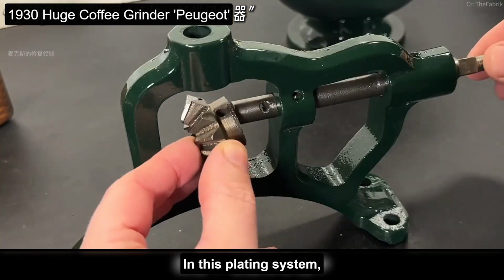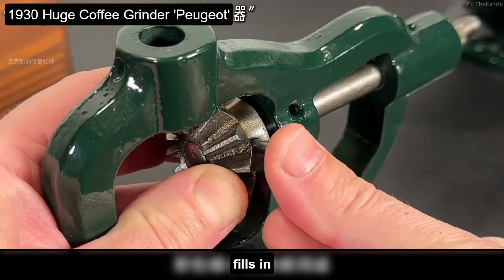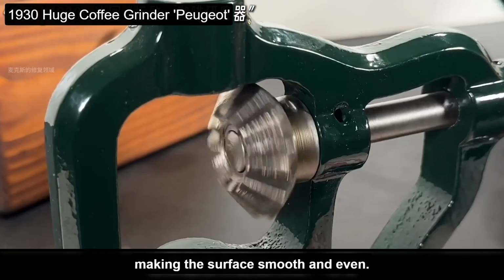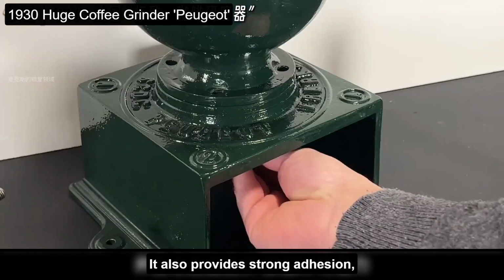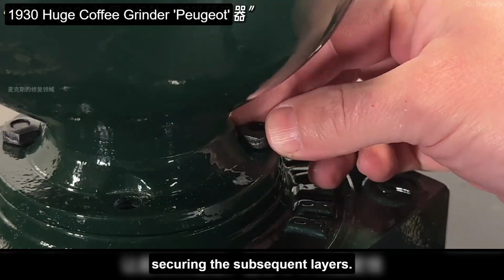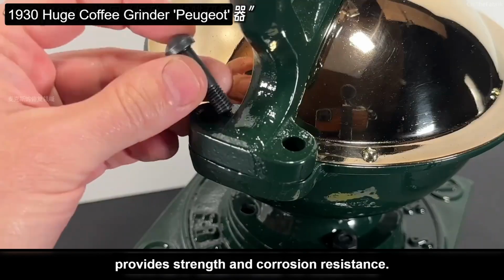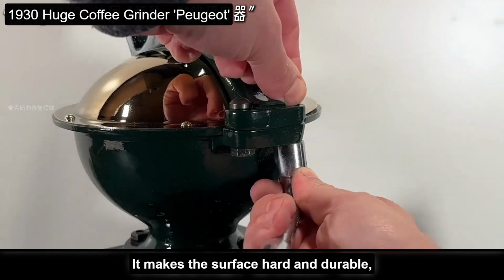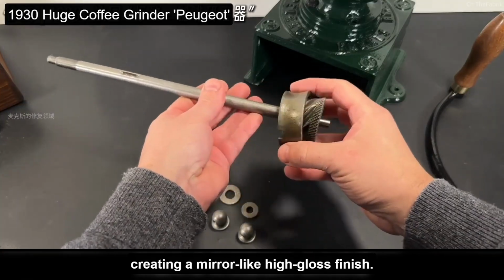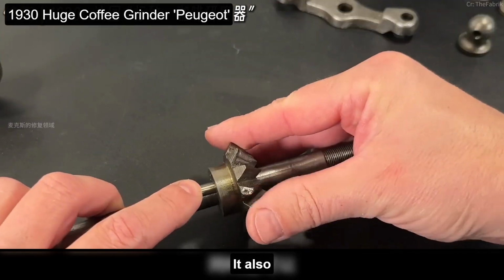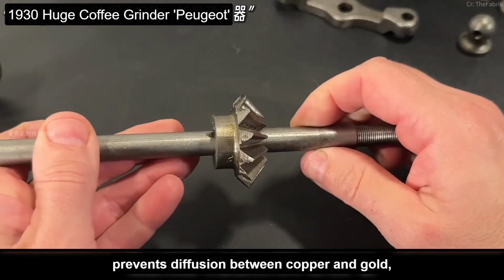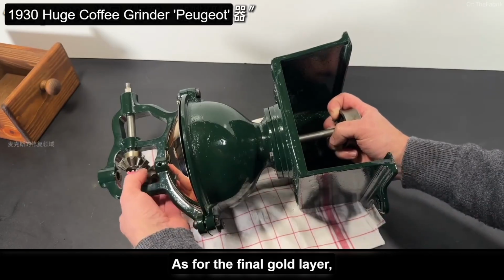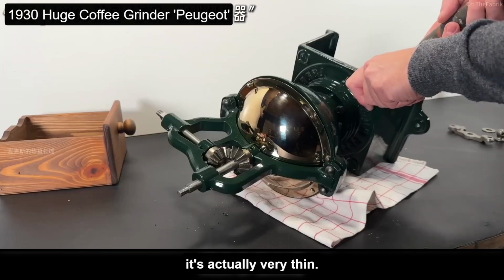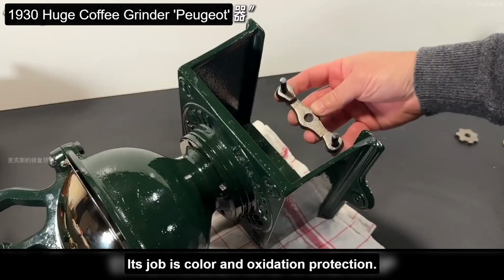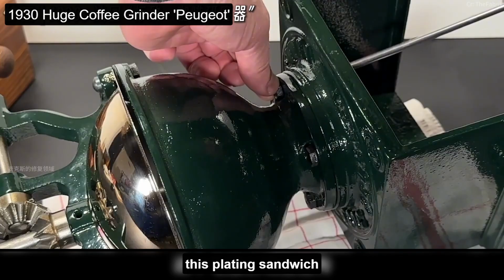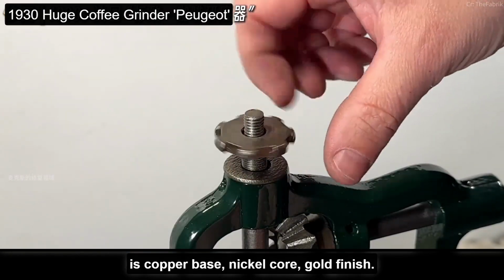In this plating system, the innermost copper layer fills in tiny scratches and flaws, making the surface smooth and even. It also provides strong adhesion, securing the subsequent layers. The middle nickel layer provides strength and corrosion resistance. It makes the surface hard and durable, creating a mirror-like high-gloss finish. It also prevents diffusion between copper and gold, so the gold doesn't discolor. As for the final gold layer, it's actually very thin. Its job is color and oxidation protection. In summary, this plating sandwich is copper base, nickel core, gold finish.